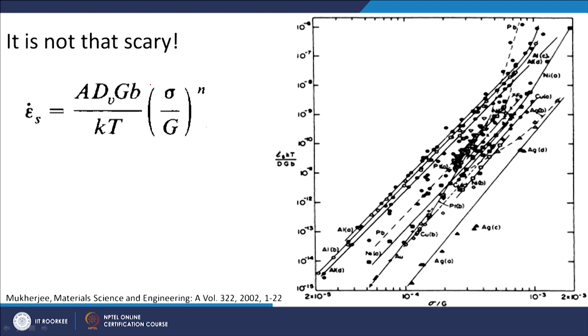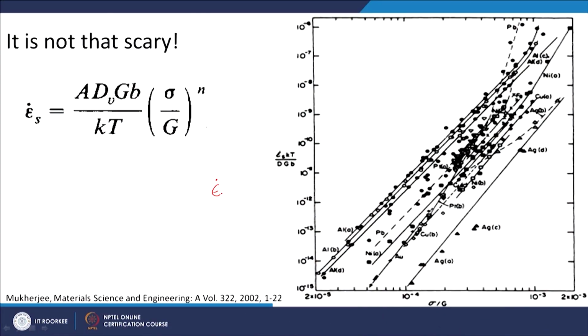So the idea is that you plot parameters. So if you see on the y axis, the parameters are like this, it is not visible clearly, so I am just plotting it here, okay. So basically what we are doing, kT is taken here, okay, and this particular parameter is taken in the denominator, so that is how you have got this y, okay. So now when you have done that, okay, what remains is sigma by G, okay. So sigma by G is taken on the x axis, so you are normalizing the stress with shear modulus, and that you are plotting on the x axis, okay.